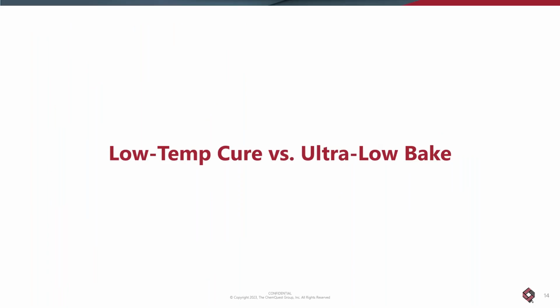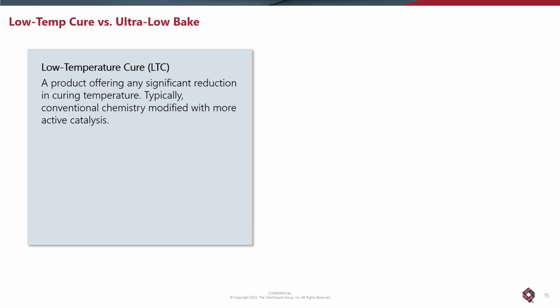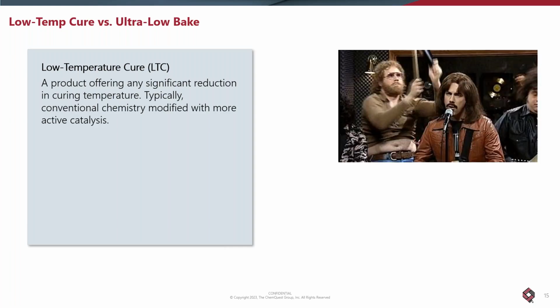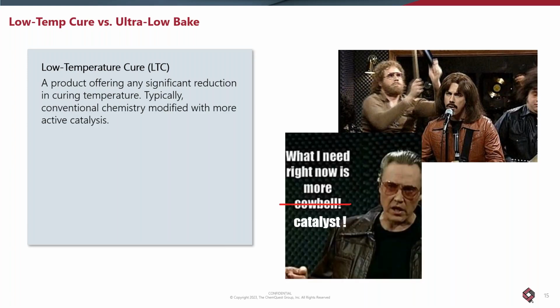Now let's differentiate between low temperature cure and ultra low bake, because that's going to be the rest of the presentation. Low temperature cure is basically reducing the traditional bake temperature of powder coatings, which is somewhere between 175 and 200 degrees Celsius, by playing with the melt viscosity a little bit, making a minor tweak, and adding more catalyst. The concept is: put more catalyst in. And anybody who's a fan of Saturday Night Live might know where I'm going with that one. So, just adding more catalyst.